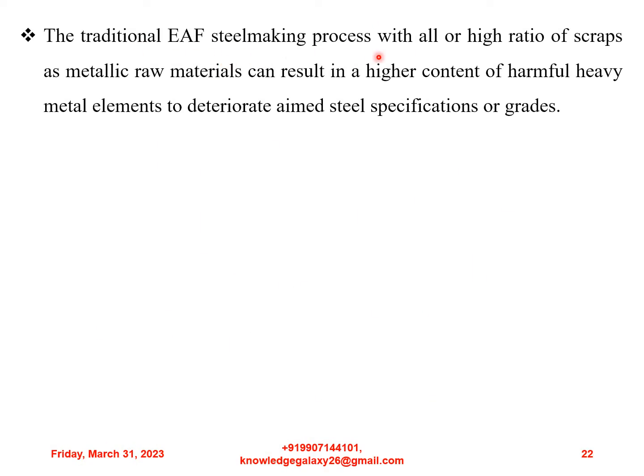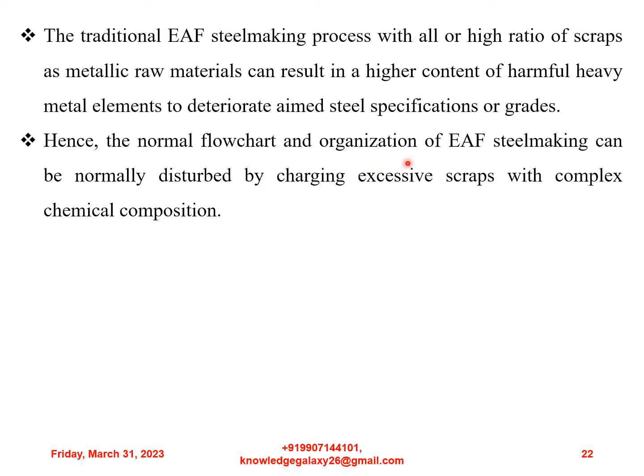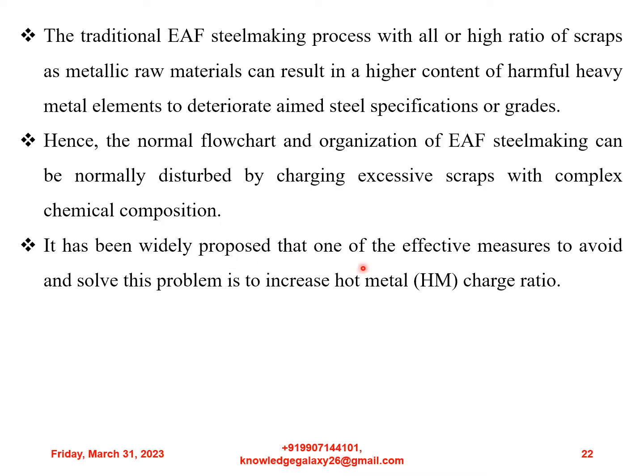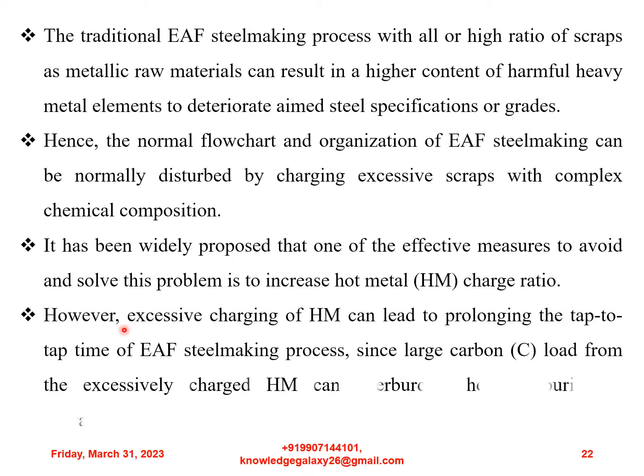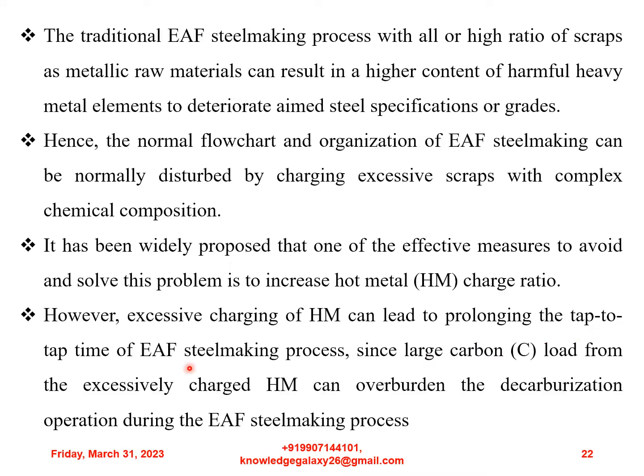Moving on, the traditional electric arc furnace steelmaking process with all or high ratio of scraps as metallic raw materials can result in a higher content of harmful heavy metal elements to deteriorate aimed steel specifications or grades. Hence, the normal flow chart and organization of electric arc furnace steelmaking can be disturbed by charging excessive scraps with complex chemical compositions. It has been widely proposed that one of the effective measures to avoid and solve this problem is to increase hot metal charge ratio. However, excessive charging of hot metal can lead to prolonging the tap-to-tap time of electric arc furnace steelmaking process, since large carbon load from the excessively charged hot metal can overburden the decarburization operation during the electric arc furnace steelmaking process.